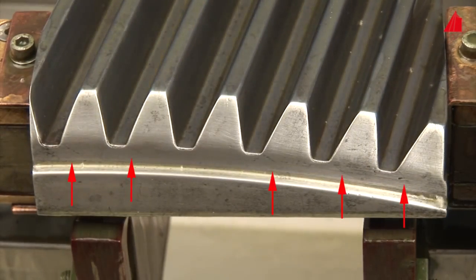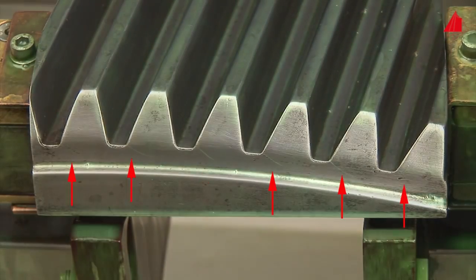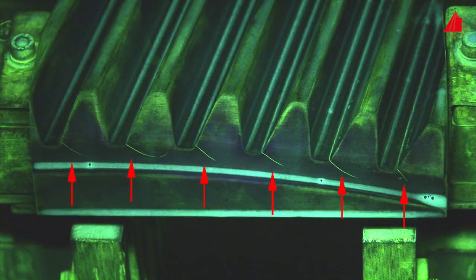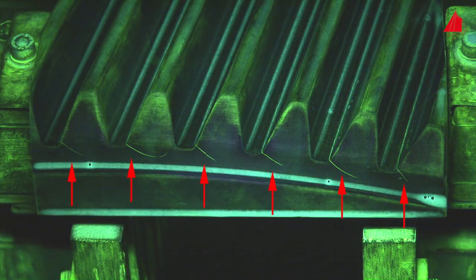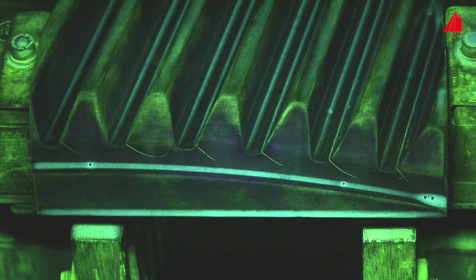Already in daylight there are indications of cracks, and again they are best visible under ultraviolet light while darkening the daylight. The visible cracks are so-called fatigue cracks. They have been generated during the operation of the gear drive due to a mismatch of the gear wheels.